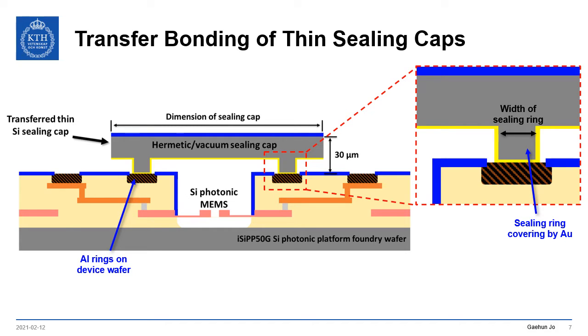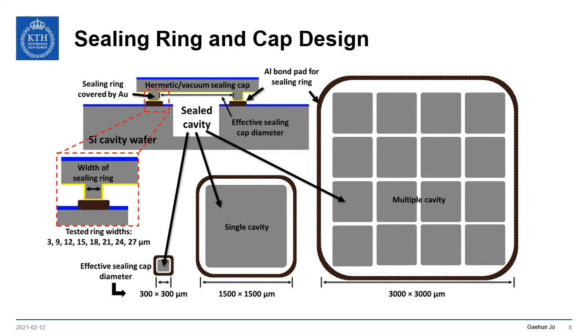Sealing rings are located along the perimeter of the caps. On the ISIPP50G silicon photonic device wafer, we designed aluminum rings which correspond with the sealing ring to enclose each photonic MEMS device in the cavity. Before demonstrating our approach on the photonic foundry wafer, we investigated the influence of the gold-coated sealing ring width and cap dimension on the resulting sealing yield.